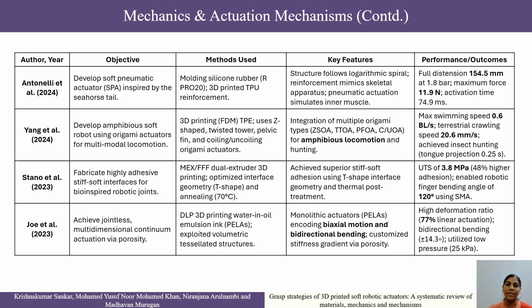Stano et al.'s stiff-soft interface optimization using T-shaped geometry and thermal post-treatment enabled 120-degree bending angles in robotic fingers with a 48% adhesion improvement. Joe et al.'s porosity-controlled monolithic actuators were able to achieve 77% linear actuation strain with a 14.3 degrees bidirectional bending, and impressively, all this was achieved using only 25 kilopascals of pressure.